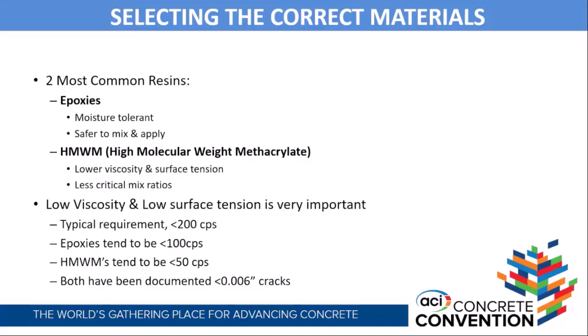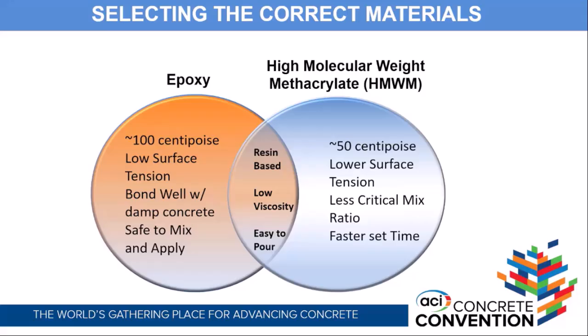And just to give you an idea of some of the viscosity requirements, typically for this application, you're looking for a resin that's going to be less than 200 centipoise, right? And epoxies can go down to 100 or less, whereas methacrylates can be 50 or less in terms of viscosity. And we have some projects that we've successfully completed where we're around 0.006 inches in terms of crack width, where we found and documented epoxies and resins being successfully applied. Okay, so again, different properties. These are the two main resins that are used for this application, but the commonality here is they're both low viscosity, and they're easy to pour in a horizontal application.